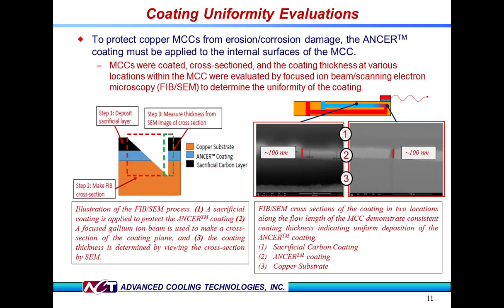In this technique, as can be seen on the left, a sacrificial layer is deposited on top of the ANCER-coated sample. A focused gallium ion beam is then used to make a cross-section of the copper plus ANCER plus sacrificial layer piece. That cross-section area is then viewed with a scanning electron microscope. A sample SEM is seen on the right.